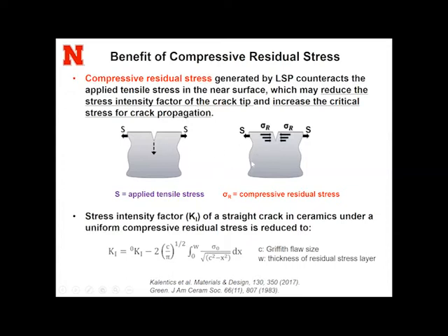And this effect can be quantified if we use another model by David Green, famous ceramic scientist. So here, his model shows if you have a straight crack in ceramic materials and you have a compressive residual stress field, the stress intensity factor can be significantly decreased. So this is used by us to explain why the fracture toughness and the bending strength are enhanced after laser shock peening.